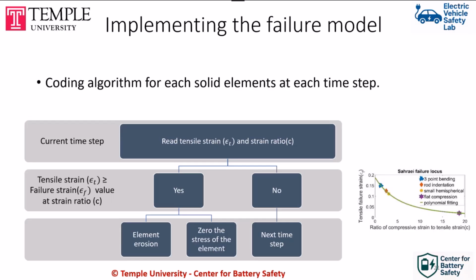cases. So the way the algorithm works is, for all of the elements in the jelly roll, you check what the ratio is. And then once you know the ratio, you check for that ratio whether it is passing the tensile failure strain in the in-plane direction. If it is passing, then you have a short circuit. If it is not passing, you are under the curve for that ratio, then you don't have a short circuit.